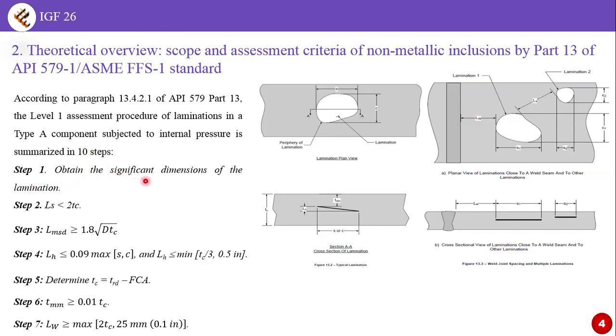Step 1 is obtaining the significant dimensions of the lamination, in the longitudinal and circumferential directions. Step 2 is verifying this criterion, where LS is the distance between laminations, and TC is the corroded thickness. If this criterion is satisfied, the dimensions of a lamination can be measured by this figure, and all laminations can be considered as a single lamination. However, if this equation is not satisfied, the dimensions of the laminations have to be measured separately, like this figure.